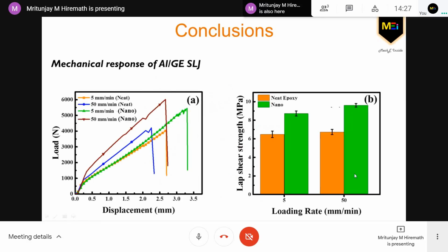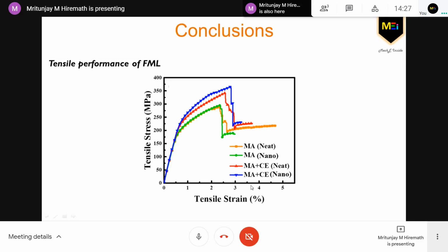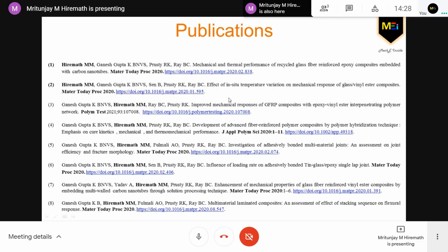So once we came to know that nanofiller embedded epoxy exhibits good bond quality compared to the neat epoxy, this was used as the adhesive in order to get the tensile performance of a fiber metal laminate. And here also we can see that when the mechanical abrasion plus the chemical etching is carried out, and the nanofiller epoxy is used as adhesive, it exhibits a very high stress-strain response and hence has a very good load carrying capacity compared to the conventional neat fiber metal laminate. So in order to have more details about this, you can go through my publications here. You can have a good referencing in order to refer to this more.